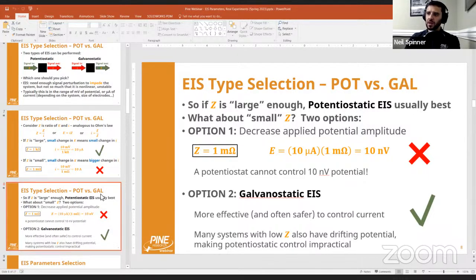Practically, there's something about galvanostatic impedance. It's more fundamentally like, okay, most of the time with galvanostatic, there's no set point. With potentiostatic, you're picking a potential. Sometimes it's OCP, but it's not always OCP. You might pick 200 millivolts, 500 millivolts, and you're sitting on there and you're doing your impedance. Well, that can sometimes change the system. Now, of course, it should be steady state. It should be stable and linear and causal, and then that makes it valid impedance. But that's not always the case, right? Sometimes you have stuff happening on your electrode, and that can affect the data.